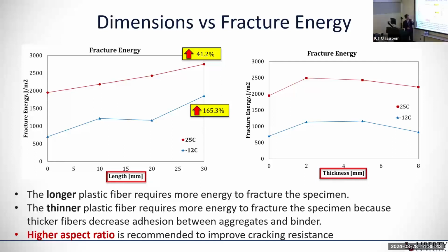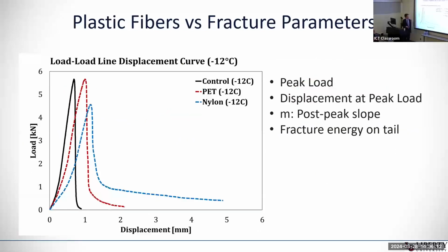And then we did the same thing, keeping the length of the fiber at 20 and increasing the width of the fiber from 2 to 4 and 6. But you don't see a continuous increase in this case, because if you increase the width, it decreases the aspect ratio of the fiber. As you have wider and wider fibers, it creates a weaker surface more and more. So that's what we found.